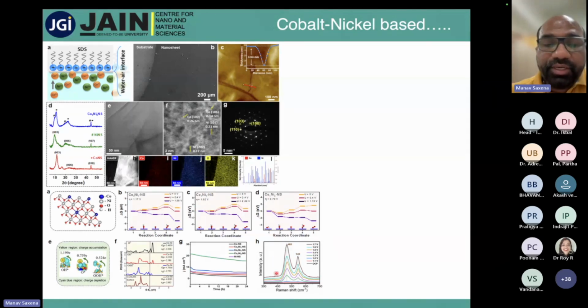Now figure H is the interesting one out of that. Figure H is about the in situ Raman. We are doing the charge storage analysis. We are charging, we are discharging, and we are doing in situ Raman, and we can find the formation of cobalt and nickel oxyhydroxide. It means the cobalt and nickel +2 is changing to +3 oxidation state, and upon discharging it is coming back. So at different potentials we have done all the analysis, and we found the mechanism of how it is going in the ultrathin film, because for the bulk material it is well known, we can do it even with XRD, but for the thin film it is challenging.